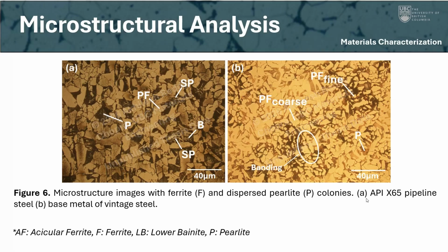Versus in image B, for the vintage steel, we do see both coarse and fine grains of ferrite. So we can see, let's say, in the pearlitic depleted regions, we have a greater accumulation of coarse-grained ferrite. And in the pearlitic rich regions, basically the areas that show more black color and contrast, the ferrites are finer.